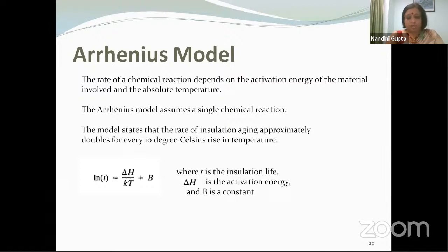And any aging process which can be expected to depend on chemical changes, or for whatever physical or engineering reason you can approximate that it behaves in the manner of chemical reactions, can be governed by the Arrhenius model for aging. But you should remember that the Arrhenius model assumes a single chemical reaction. So therefore, there will be some approximation there. This Arrhenius model for aging, which is based on the Arrhenius chemical reaction rate, states that the rate of insulation aging approximately doubles for every 10 degrees Celsius rise in temperature. So this is something that you would use for thermal aging conditions.